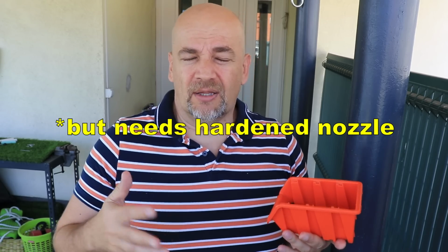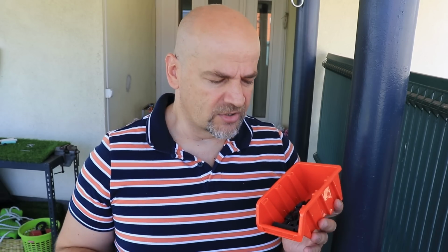And other conclusions. Well, I think this is a great material, but not because of the mechanical properties. Okay, it is better on bending and impact test and maybe a little bit on a creep test. But on the other side we have that weaker layer adhesion. We have to keep in mind when we create our designs or choose the printing orientation. But the reason why I like this filament is its printability. It's much easier for printing compared to the regular PC blend. So we have less warping, better dimensional accuracy, and thanks to those carbon fibers, the shrinking after annealing is much smaller compared to the non-carbon fiber versions.